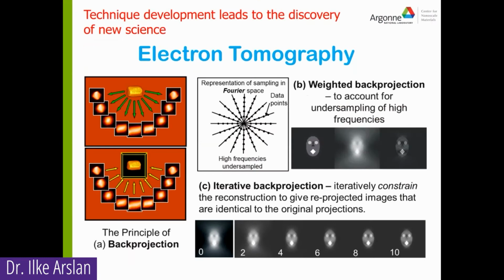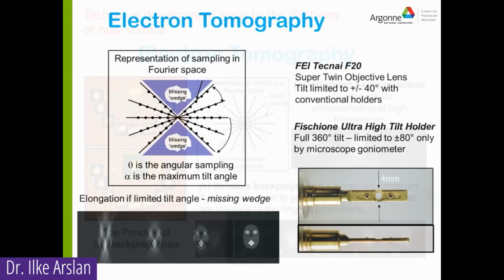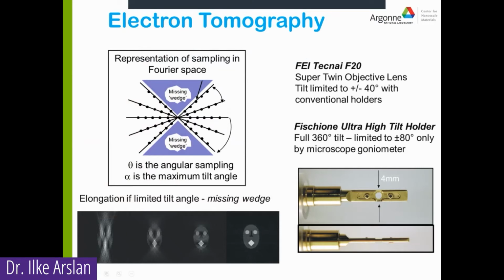So I'm going to skip over these. And in electron tomography, you have a small holder, a tip that is smaller than usual. It's 4 millimeters rather than just a millimeter over our 3 millimeter grids. And you tilt it to many different angles. And then, of course, there are some artifacts if you don't tilt high enough, which I don't have time to go into how you can overcome those.